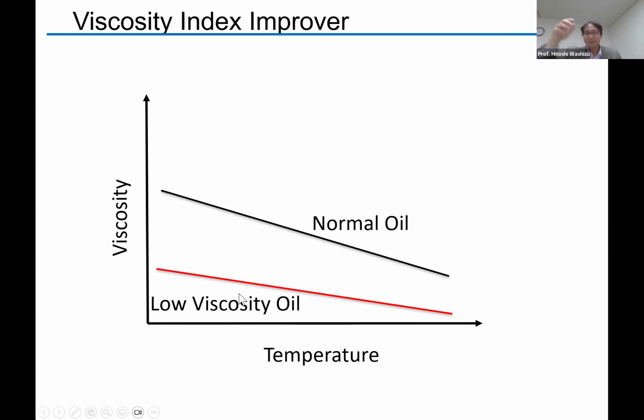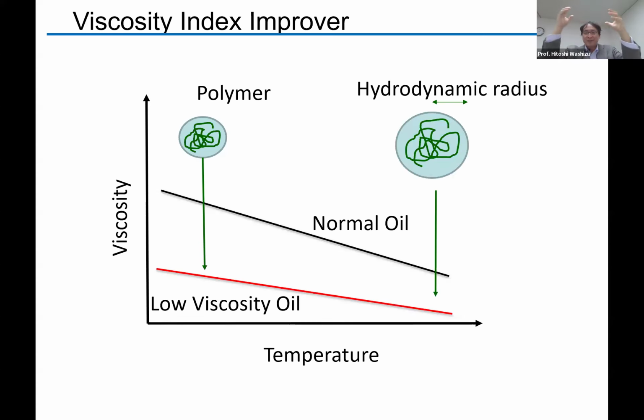But after you start the engine, heat is generated, the temperature rises, and then the viscosity is too low to make the lubrication film in the engine. So we put some polymer here. In the low temperature, the polymer is very small, but in the high temperature, it becomes larger due to the thermal effect. So we can improve the viscosity and make it flat-dependent on the temperature. This is named the viscosity index improver.